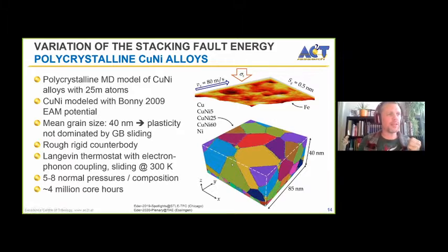We made sure that our grains are large enough, 40 nanometer grains, so that our plasticity is not dominated by grain boundary sliding. So we're solidly in the Hall-Petch regime. And only at 300 Kelvin, only at room temperature, we already blew 4 million core hours on this little project.